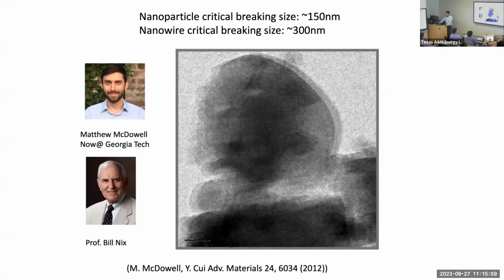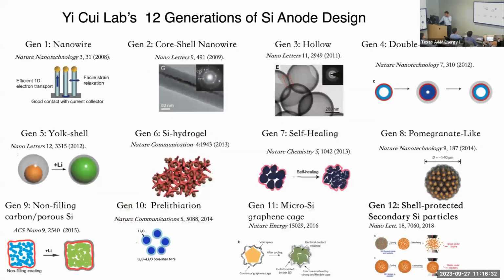We use a tool like this to figure out what's the critical breaking size for a spherical particle. It needs to go down below 150 nanometers in diameter to minimize breaking. If it's too big, it's going to break. So this has been providing a guideline for the whole industry, on what the critical breaking sizes are that industry needs to pay attention to in order to avoid breaking. My lab has been through 12 generations of design to avoid breaking.